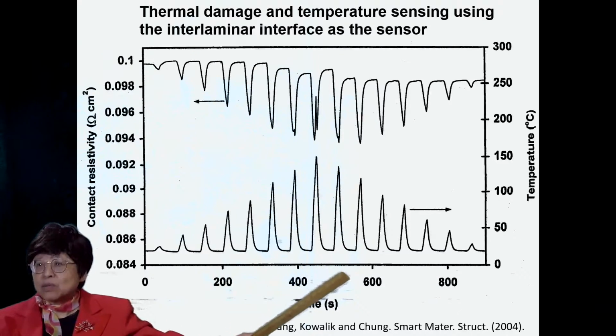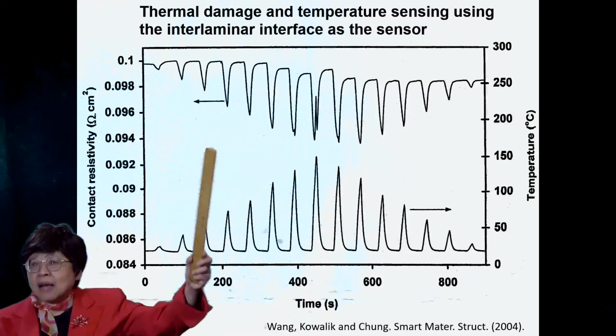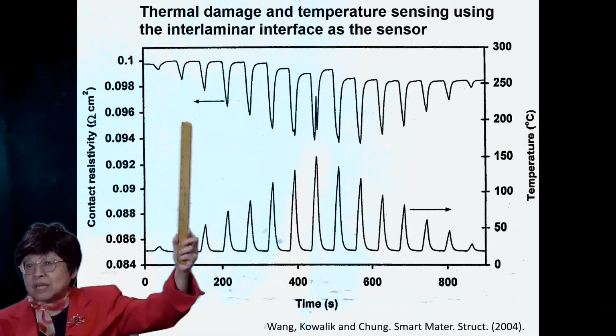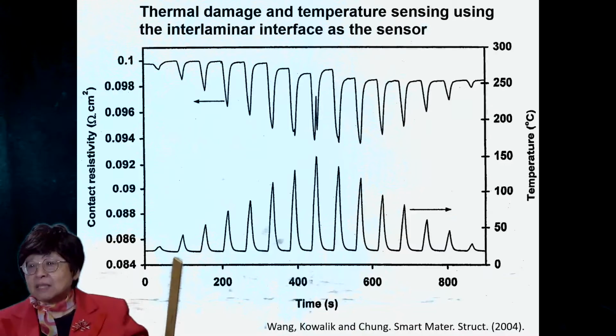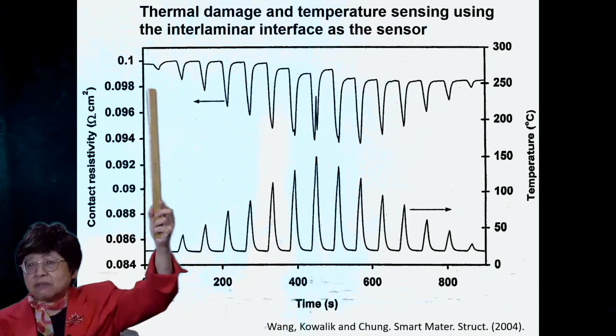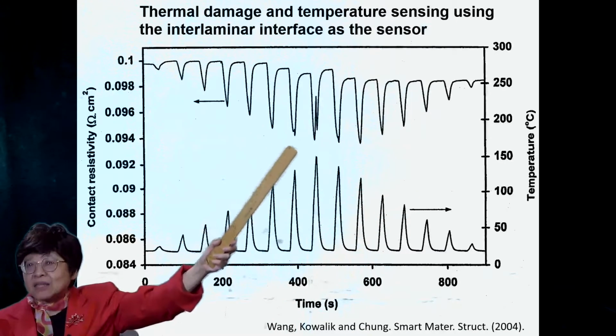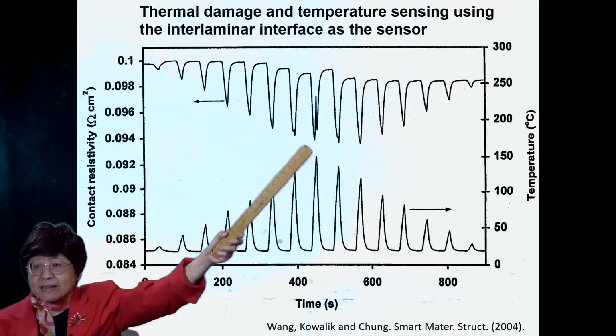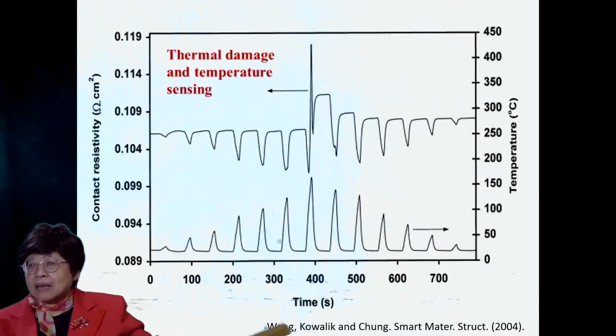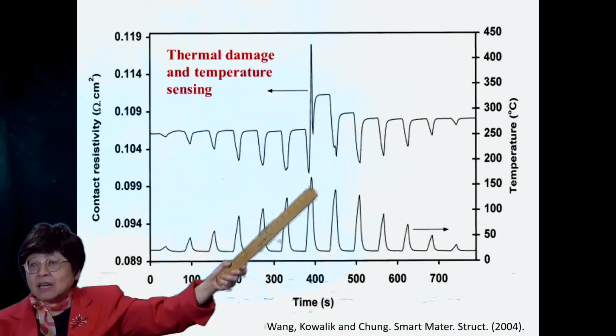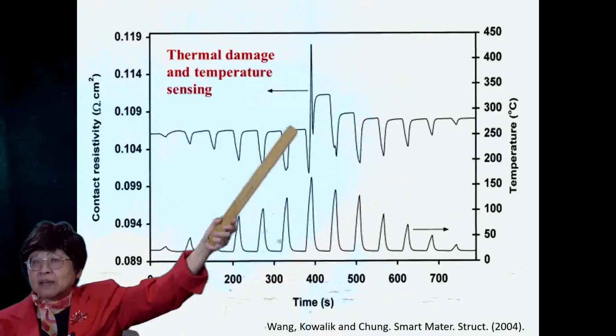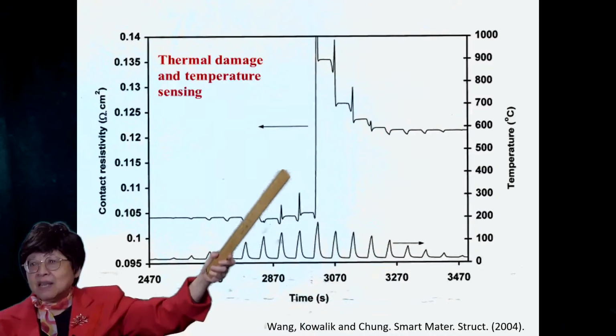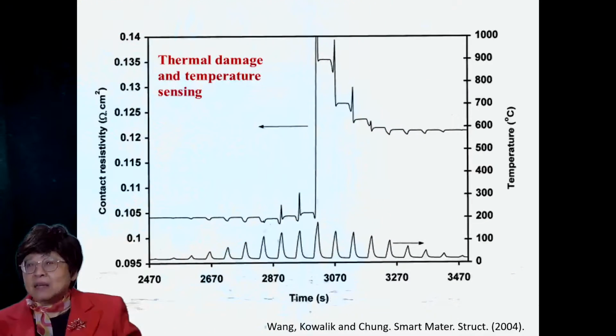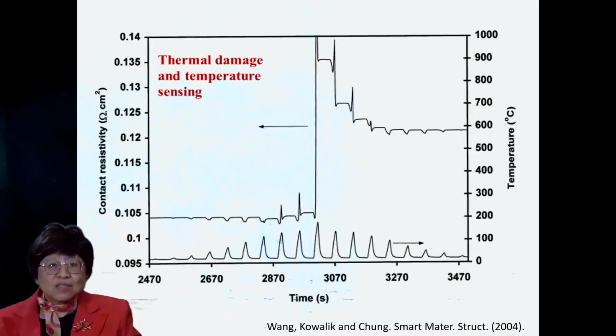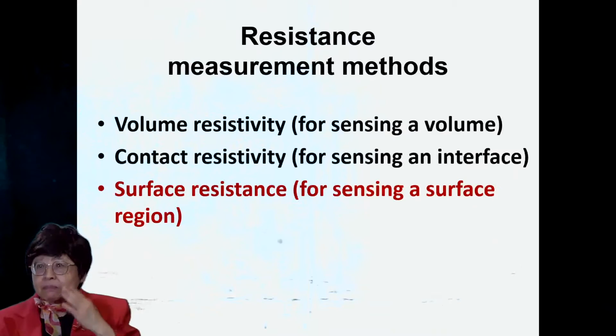Here at the bottom shows temperature variation, and upper curve shows the contact resistivity variation. Every time the temperature goes up, the contact resistivity goes down. But at the highest temperature, there's an upward spike in the contact resistivity indicating damage. And if the highest temperature is a little higher, the thermal damage becomes more and the spike becomes more. And this is even more. So we have temperature and thermal damage sensed at the same time.